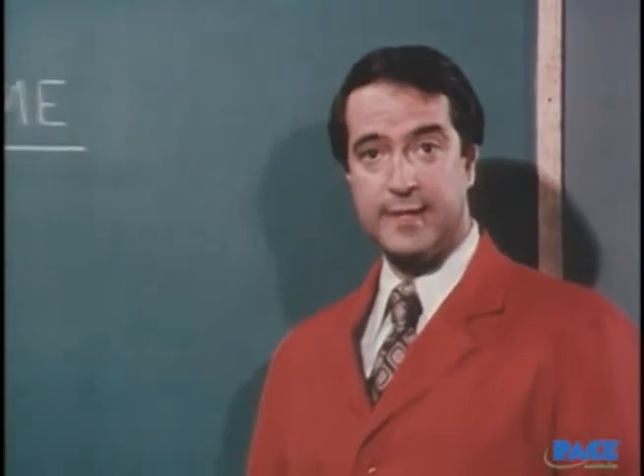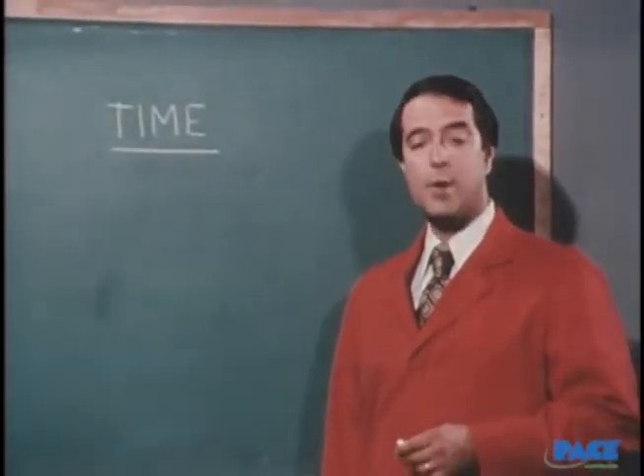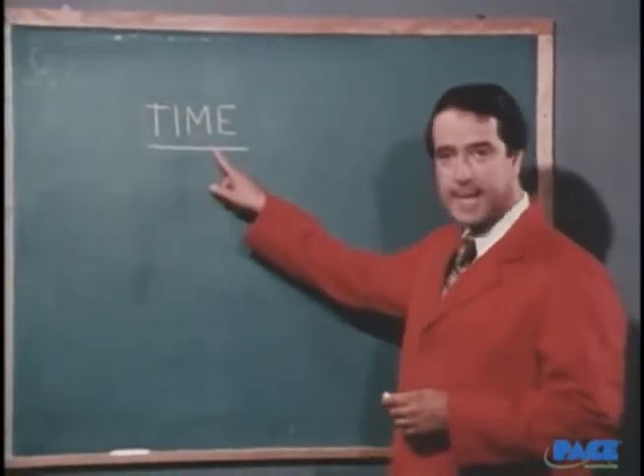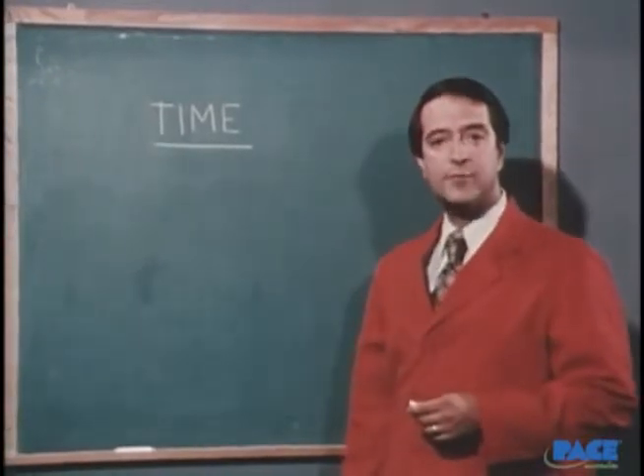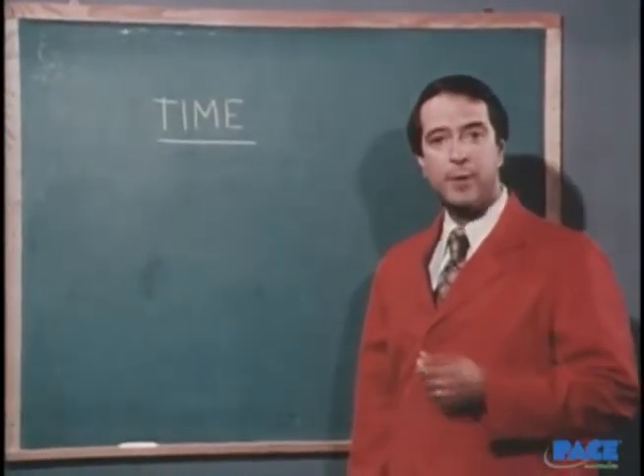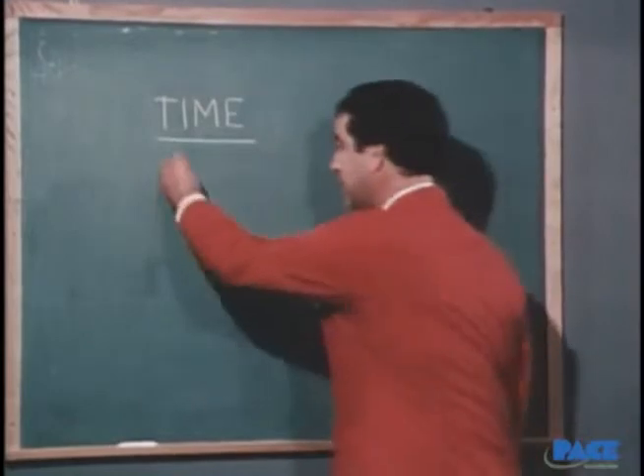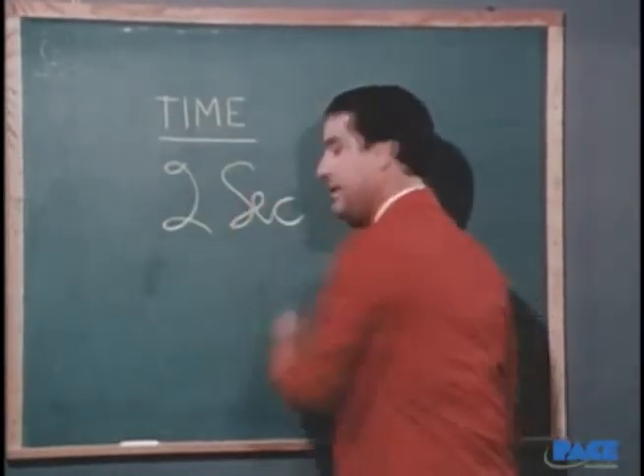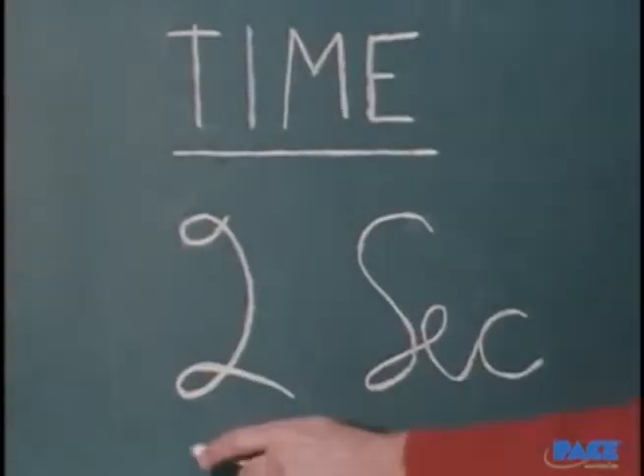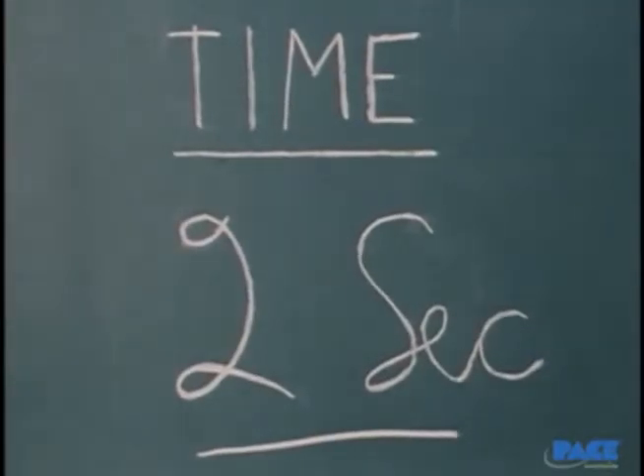So now we've seen that there are more things than just the temperature of the iron tip that affect how quickly the joint is going to heat up. It's become a complex control problem with a number of variables to it, each influencing the other. And what makes it so critical is time. The general rule is, for high reliability soldering, apply heat for no more than 2 seconds. Any longer than this, and you'll begin to damage the board.